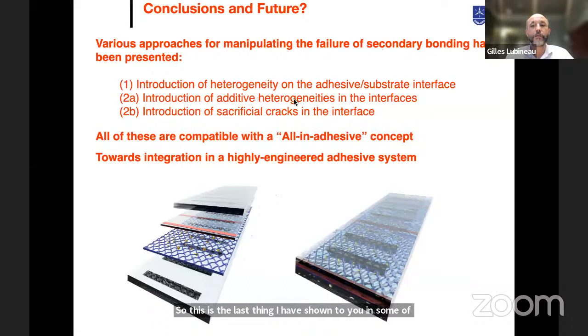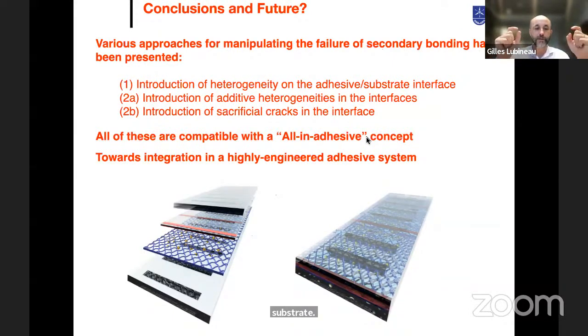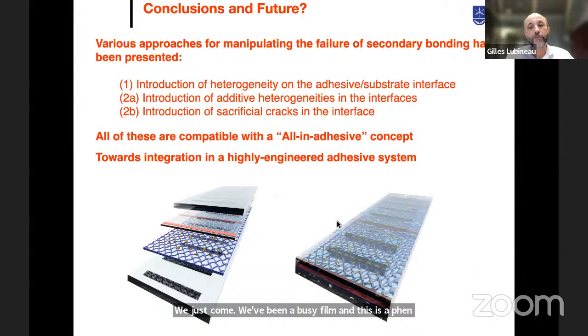Sometimes these heterogeneities, instead of thermoplastic, can be sacrificial cracks. So this is a third approach that I did not present today. But what is important is that all of these are compatible with what we call an all-in-adhesive concept. That means that we don't touch the substrate at all. We just come with an adhesive film, and this adhesive film is encapsulated in between two substrates. So there is no modification of the performance of the substrate.